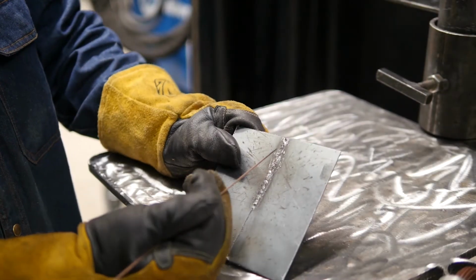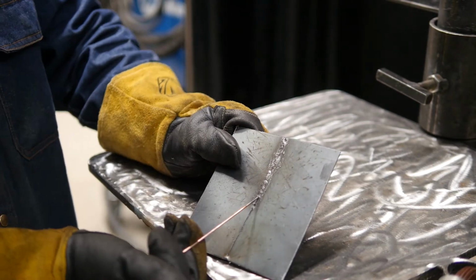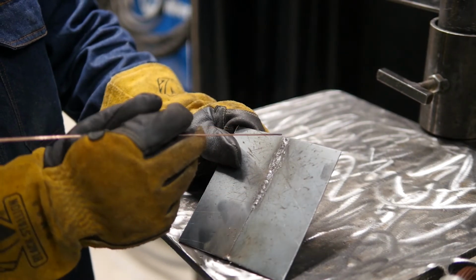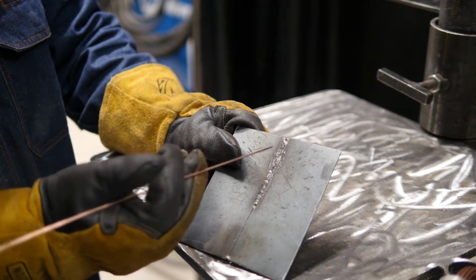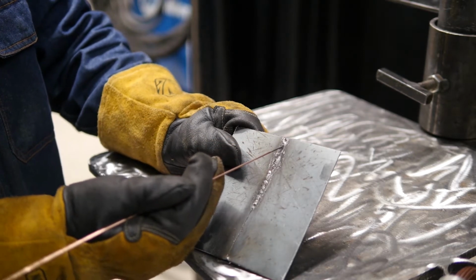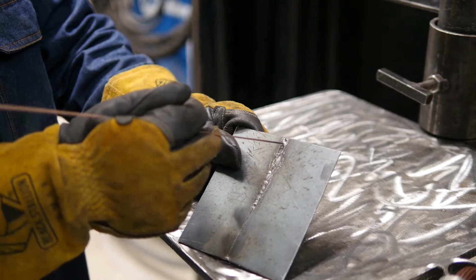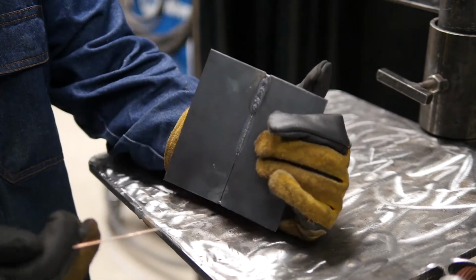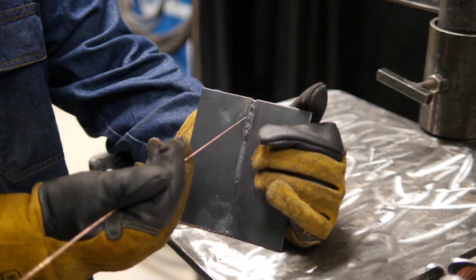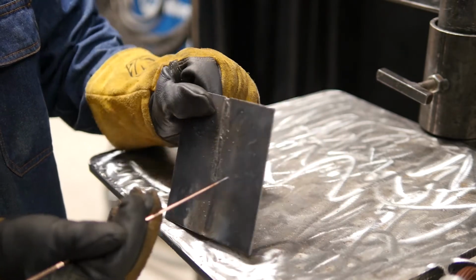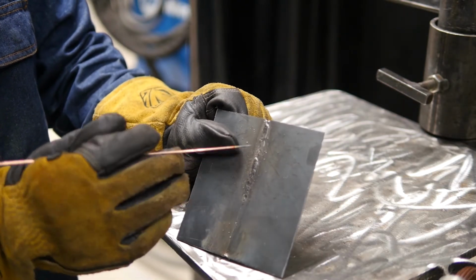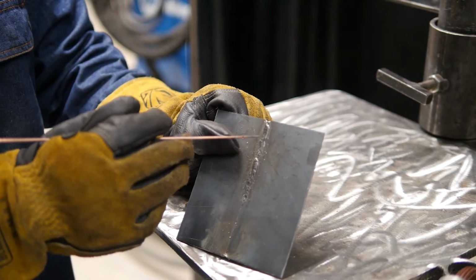All right, here's our two welds. This is the vertical weld and this is the flat weld. And I didn't like the vertical weld. The procedures were a little bit too high. I had a little bit too much amperage and it was pushing through the plate. We can see the backside really smeared around and both surfaces are concaved, which is not what we want. And I have a little pinhole here. I didn't really like that.